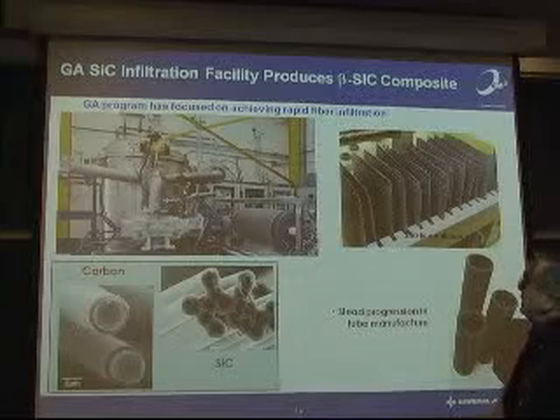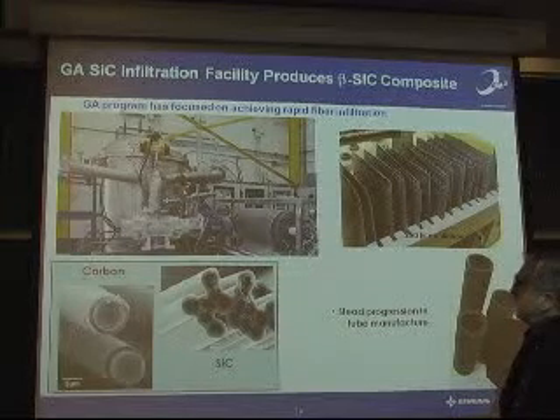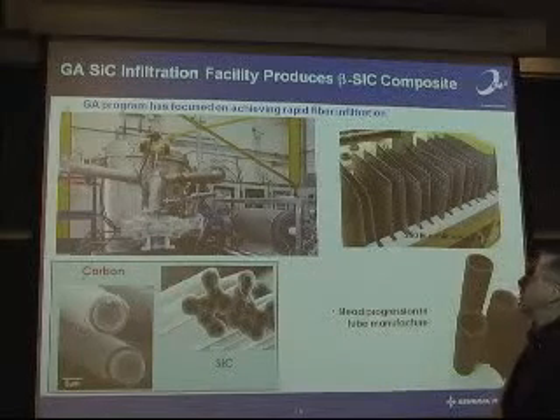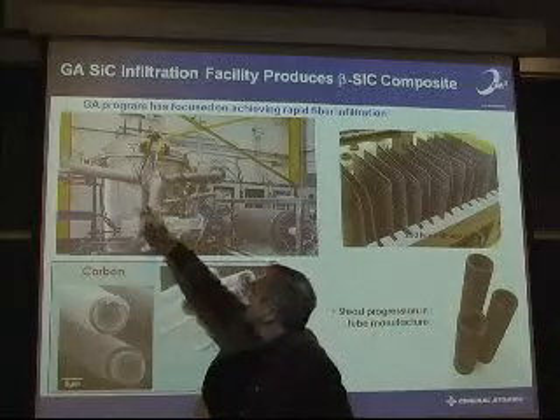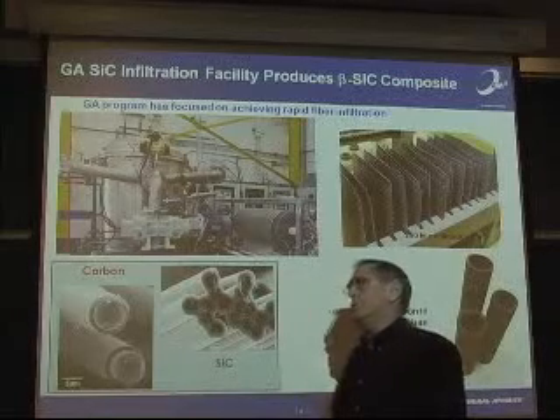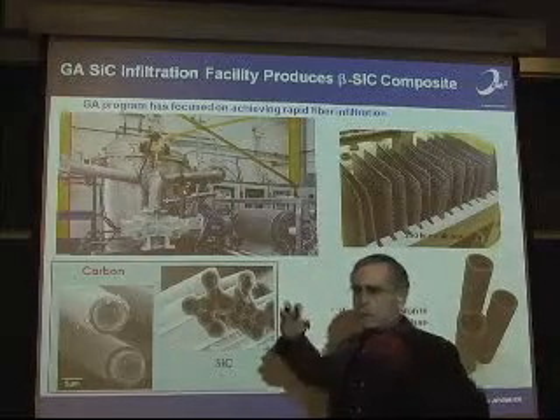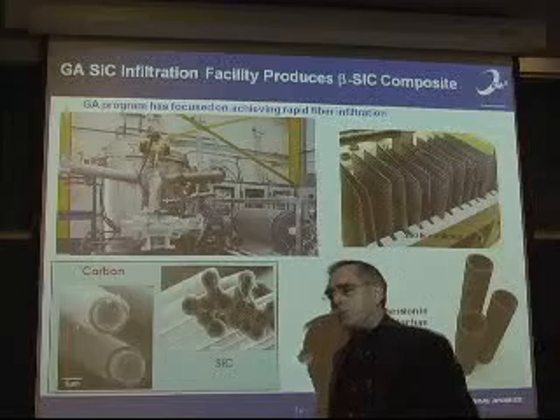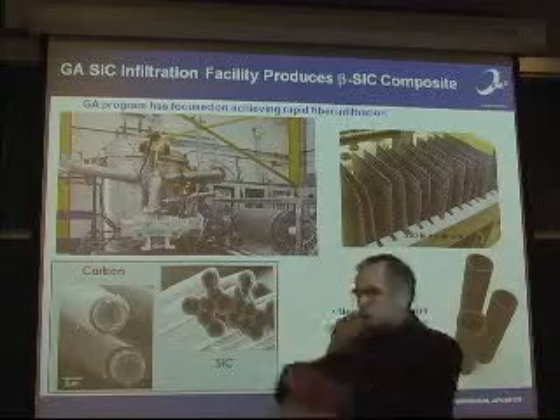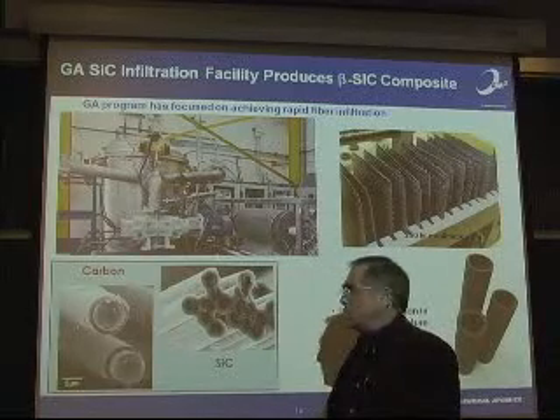And then we built this silicon carbide facility for making silicon carbide by a gaseous infiltration process, which you decompose methyl trichlorosilane. There's two furnaces here. This is what we call ICVI, meaning isothermal chemical vapor infiltration, and the molecules of MTS, methyl trichlorosilane, find their way into the weave of silicon carbide fibers and then decompose and leave silicon carbide, and hydrochloric acid has to come away. Well, it takes about 300 hours to make about 1 millimeter of material by that method,